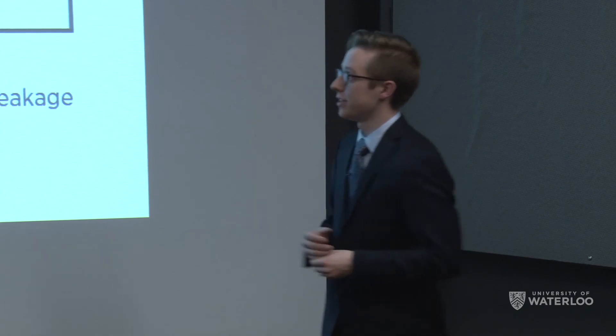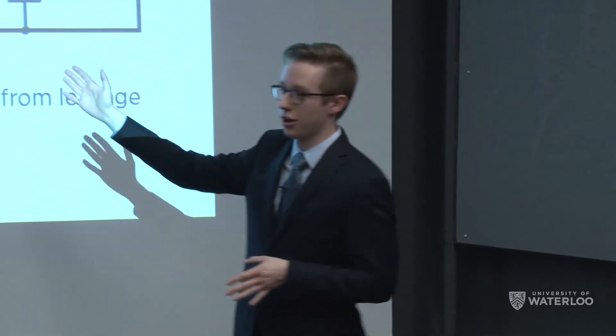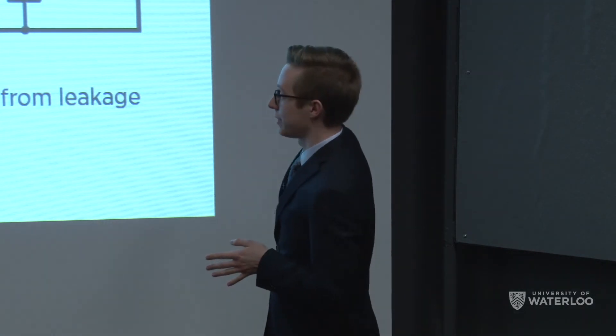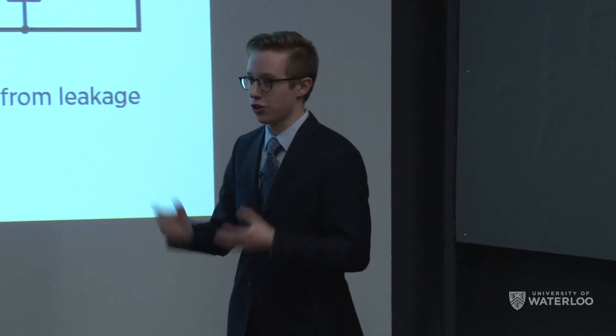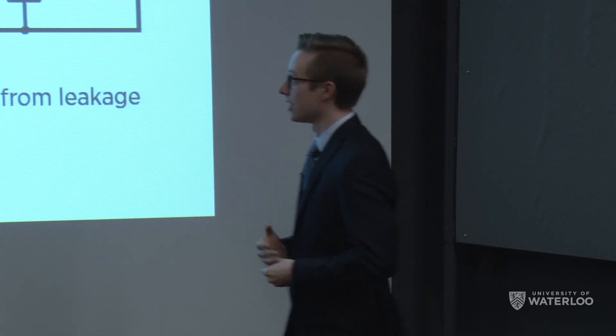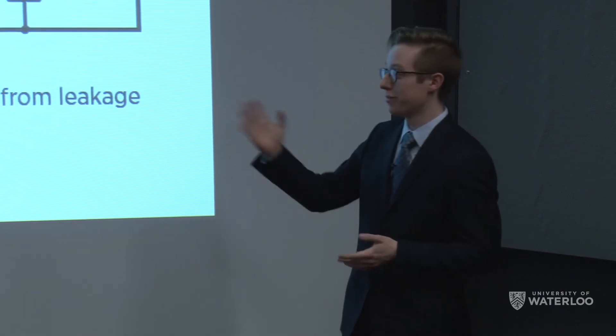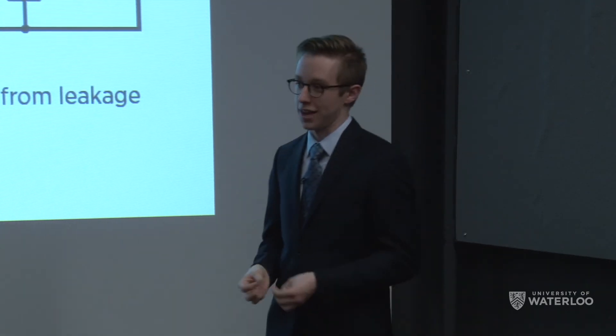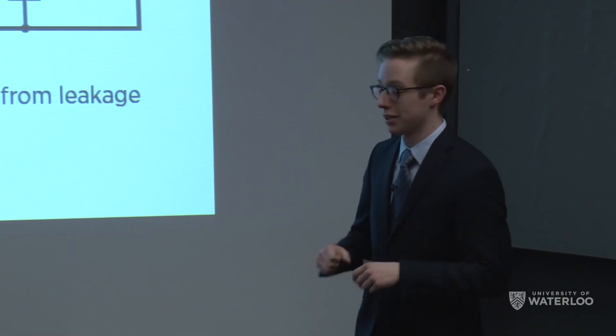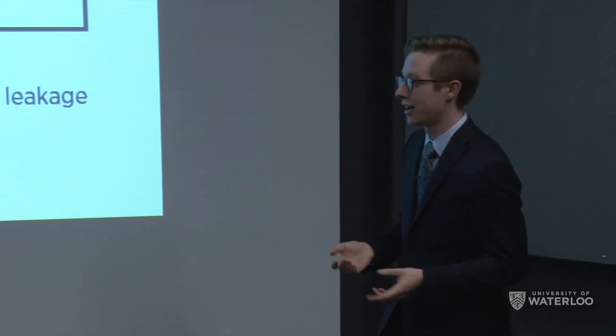Addressing the capacitive leakage: we identified two areas of potential issue at the inlet and exit of the activated carbon slurry, where the current collectors are actually interacting with the water stream before it is desalinated. As a consequence, we concluded that almost half of the cell's capacitance is coming from these areas, meaning the effective potential seen across the desalinating region was quite a bit lower — which may be why we didn't get any effective deionization. A correction would be to insulate that portion of the current collector from the flow stream.